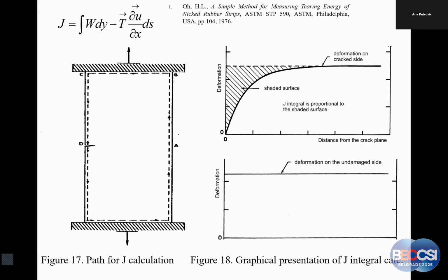Now, this is probably the simplest possible case that one can get. Clamped plate, no rotation, no bending, just tension, and distribution of strains along the cracked side and along the uncracked side. For the cracked side, this one, it goes to zero at the crack, no deformation. When the distance from the crack is long enough, they are the same. In other words, the difference between them, this shaded surface, is actually J integral in its simplest form.